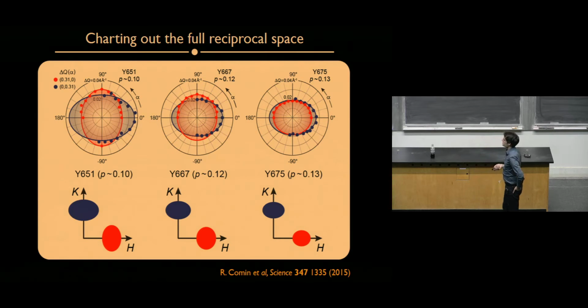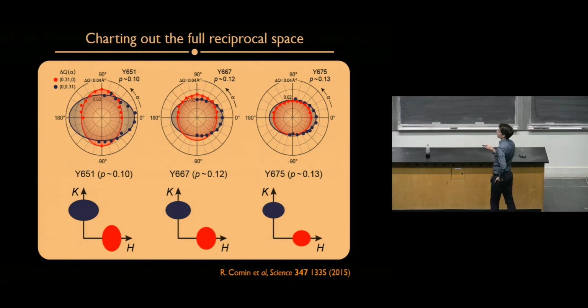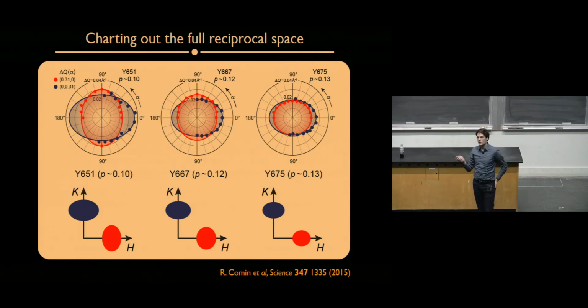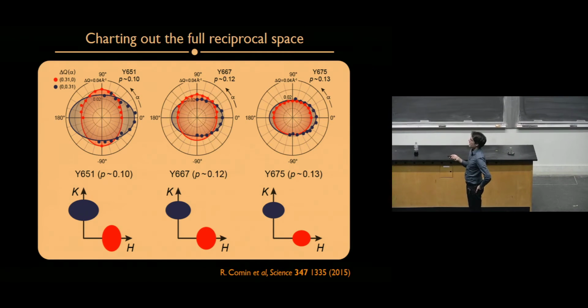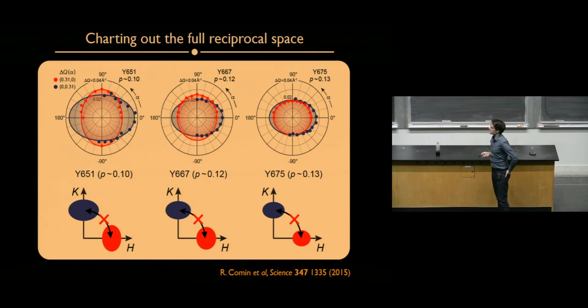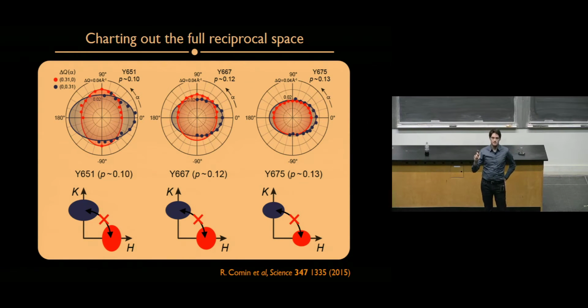And this is one of the cuprate samples. It's called YBCO sample. It's one of the cuprate compounds as a function of doping. This is 10% holes per copper, 12%, and 13%. And we look at the shape of these peaks in reciprocal space along one reciprocal axis, which is H or QX, they're the same thing, and along the other reciprocal axis, K or QY. And we realize that these shapes are not the same.